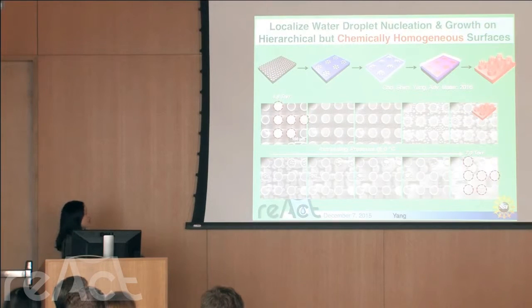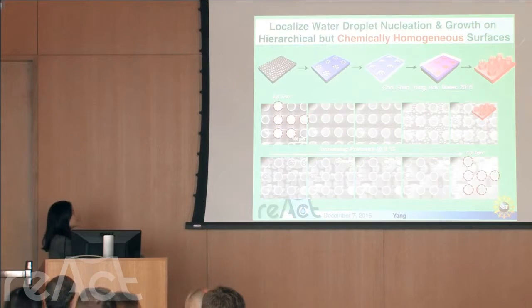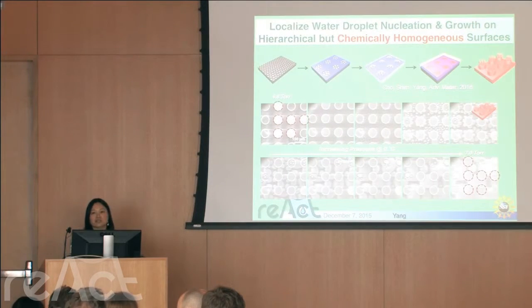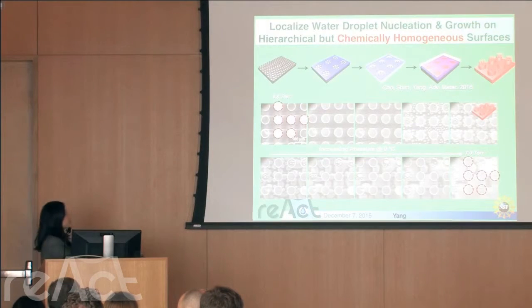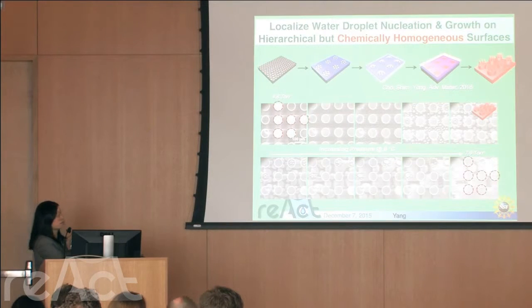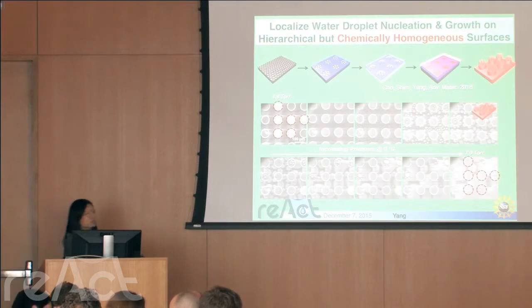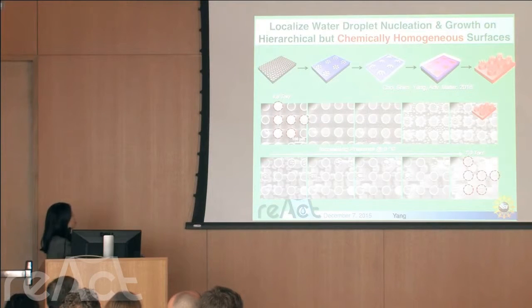So we fabricated this. So this nanopillar is about a few hundred nanometers, and underneath we have micron size. So if the theory is correct, then on these nanopillar covered regions, we should not see the nucleation. All right? And this is exactly what we saw. So we purposely identified some good regions and bad regions for the comparison. So this is the environmental SEM. And we saw here, for example, this is a pillar and this is a non-pillar region.